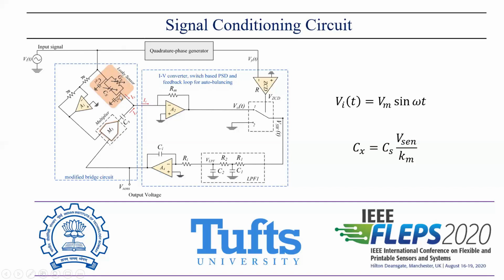So at the balance condition, when the output of the low pass filter is 0, we can obtain information about the sensor capacitance, which can be given by this equation: Cx equals Cs times Vsen upon Km. Here Km is the gain of the analog multiplier, which is given in per volt. So if we have the value of V sense, which is the output of the integrator, we can simply obtain the value of the sensor capacitance since Cs is a known capacitance. So this is a very simple and effective circuit to compensate the leakage and parasitic capacitance of the sensor and to measure the sensor value very accurately.